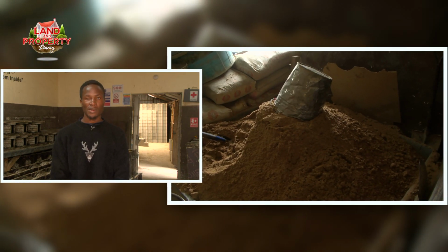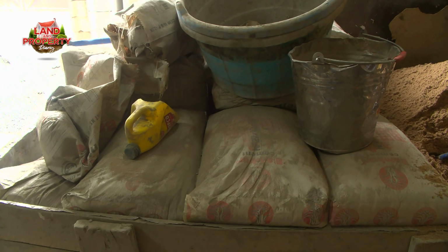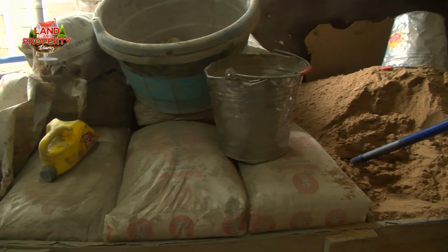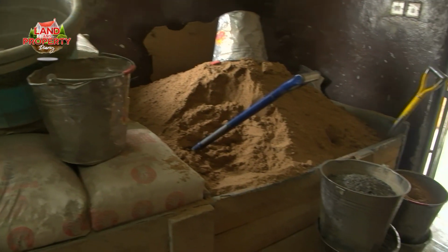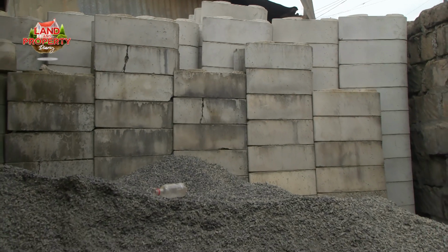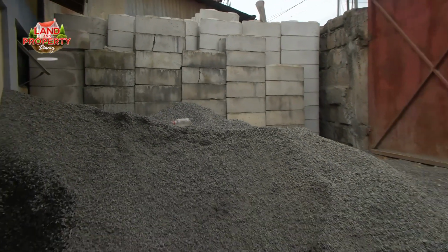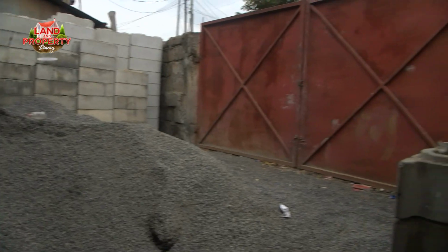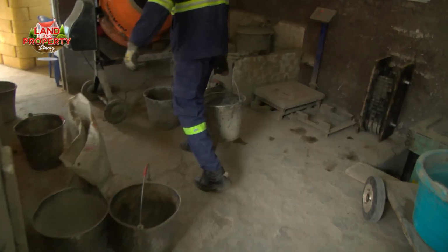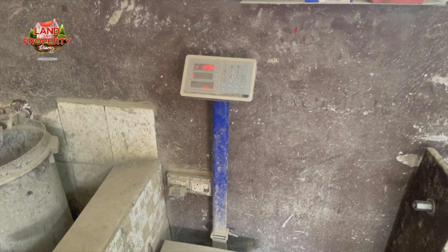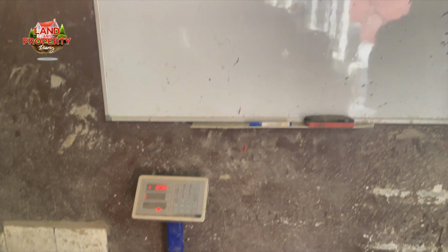We also use the river sand, which is acquired from our local rivers in the country, that is River Athi. We also utilize class 42.5 cement in the manufacture of the twist block. We also utilize the water that we get from our taps, and then eventually all those materials are carefully batched and then mixed in an electrical mixer to achieve the desired consistency and strength. So that is in a nutshell the mixing procedure.